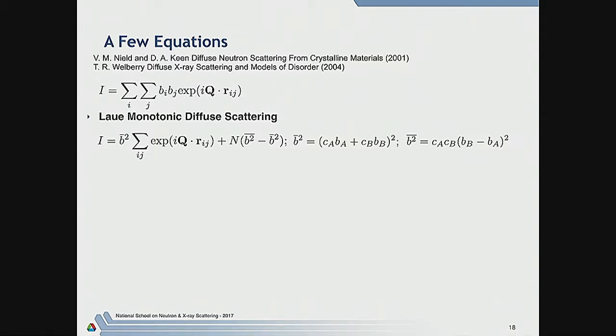Okay, so you can think of, if you have a random occupation of sites by two different atomic species with their own scattering length, that's formally exactly equivalent to having the same element but with different isotopes and different scattering lengths. And so just as with incoherent scattering, it's Q independent. So here, again with this Laue monotonic diffuse scattering, it's Q independent. So you get a constant background, whose intensity is given by the concentration of the atoms A and B and their respective scattering lengths.